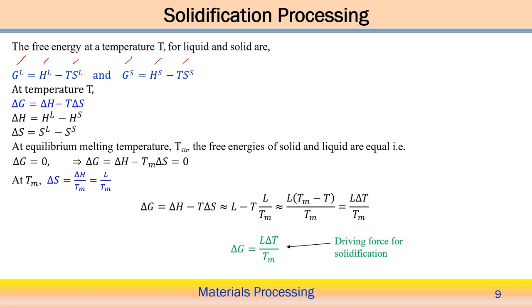Now, we can see the change of the Gibbs free energy, delta G. Delta G equals the liquid minus the solid, so delta G equals delta H minus T into delta S, such that delta H equals HL minus HS and delta S equals SL minus SS. That means the difference between the entropy of the liquid and solid phase and the difference between the enthalpy of the liquid and solid phase.